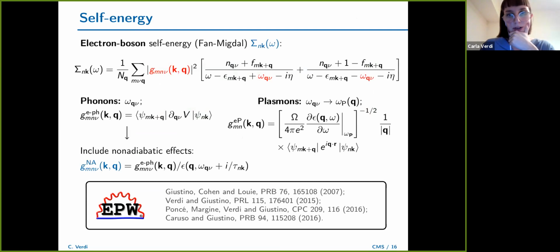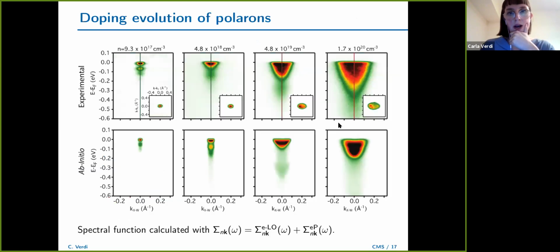So if we do calculations where we include both the electron-phonon self-energy and the electron-plasmon self-energy, then we get this sort of spectral function. At low doping, it's basically what I showed you before. And then at increasing doping, you see that we also get a satellite that has a larger energy separation with respect to the main peak. And actually at larger doping, it becomes very dim. And then we just have a kind of broad tail and no clear satellite anymore.